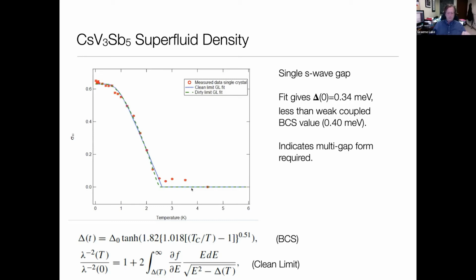So the fact that we get a significantly smaller gap tells us that we have to have multiple gaps, which is possible because you have different parts of the Fermi surface. You may have superconducting pairing on one part of the Fermi surface, which is the sort of the driving thing, and then there can be a proximity effect, basically in reciprocal space, inducing superconductivity on other bands, and they will have a significantly weaker gap because the superconductivity is not fundamentally residing there. And so what we're in the process of doing now is doing the fits.